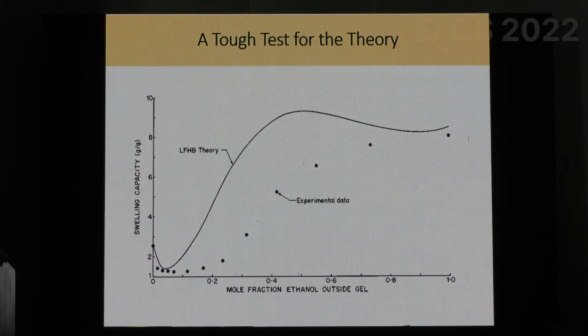We wanted to test our theory even further, and there was this very interesting experimental data that we had in the lab, which says that if I take a water ethanol mixture and put this polymer in it, it undergoes what is called a re-entrant phase transition. That is, the polymer is swollen in pure water, and the polymer is swollen in pure ethanol, but in between the polymer collapses. So it's swollen state in pure water. As you put ethanol, it collapses, and then you put more ethanol, it swells back again. So this is called a re-entrant phase transition.